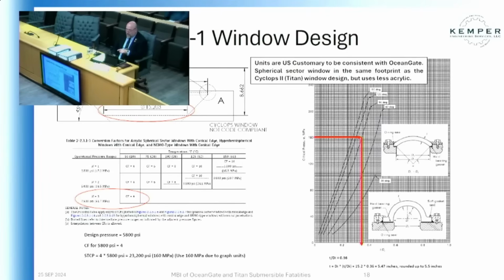And if you would have presented this to me as a good idea on its own, I would have a lot of issues. But this has 70 years of proof, and before they even did that, they had 20 years of testing to back that up. So I know this is shockingly simple for such a critical item, but when people say that Jerry Stachiw was conservative in where he put his design lines, he was, because of the uncertainty, because at that time, with the tools available, there was just not a reliable way to model this directly with mathematics like we would a beam calculation. So that is the PVHO-1 design method.